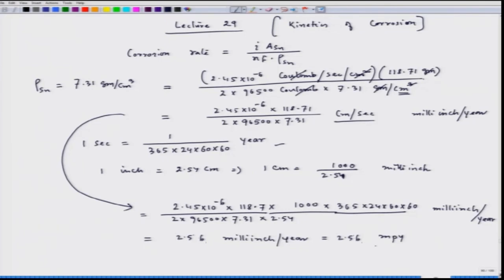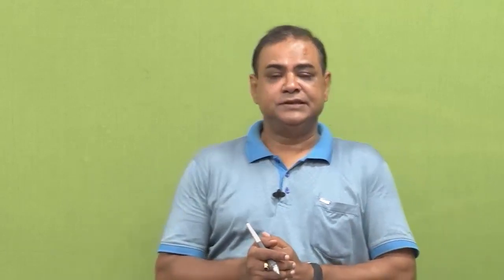So, we could see that we can express the corrosion rate by using the corrosion current density, and then we can convert it into either MDD, that means weight loss per area per unit time, and also we can convert it into MPY, which is milli inch per year. So, we can convert it into uniform as well as localized depending on the surface nature of that particular metal in that particular corrosive environment. Now, let us get a little deeper into the current density part.